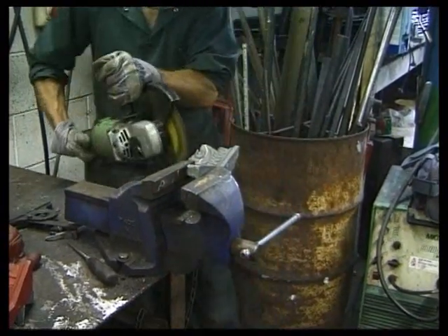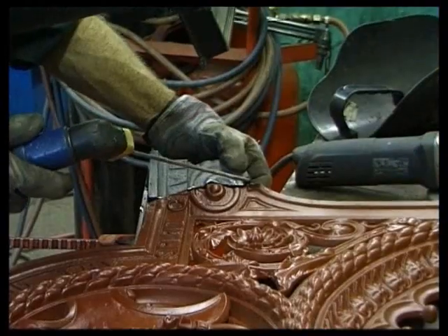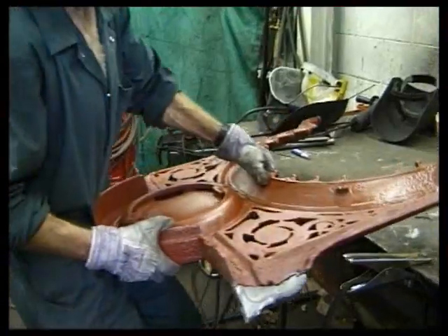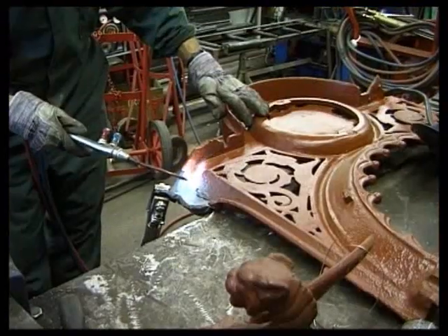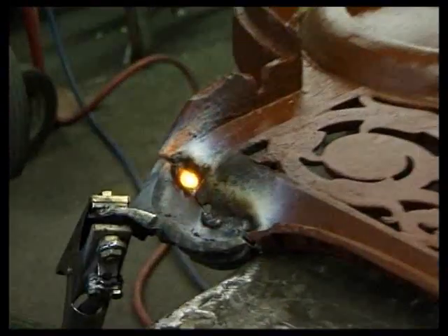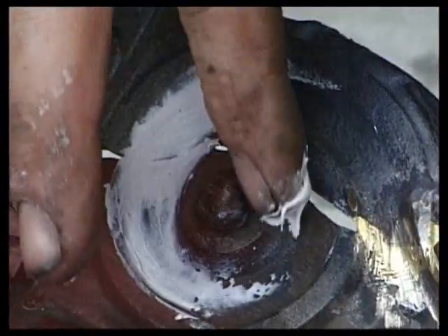The new casting may need dressing to remove the flashing line caused by slight leakage of metal between the mould boxes. It can be bolted, stitched or welded in place. Electric arc welding is fast but recommended only for non-structural parts. The very high temperature of the electric arc tends to shock and crack brittle cast iron around the weld. The whole area should therefore be preheated gently and the new piece secured by intermittent welds. The minimal amount of welding should be used on non-structural repairs, gaps being made good by a 2-pack resin.